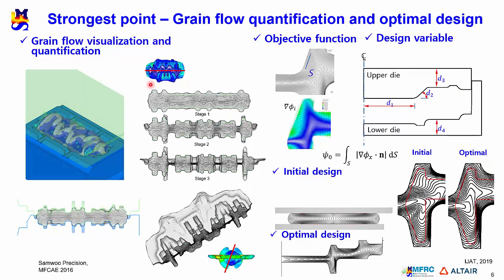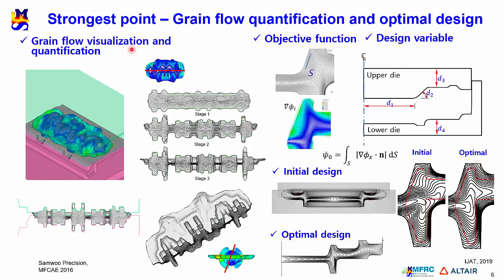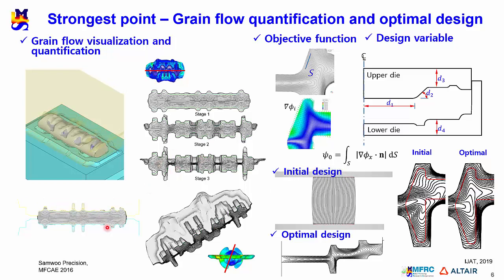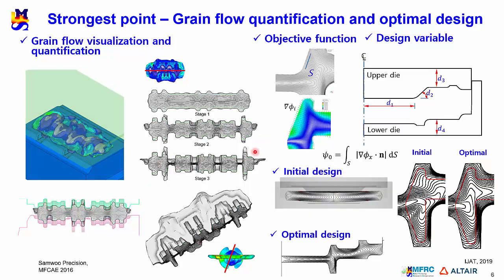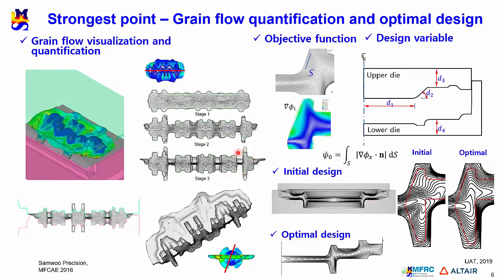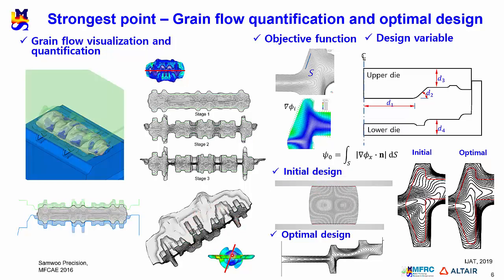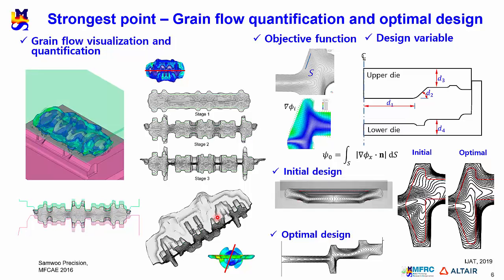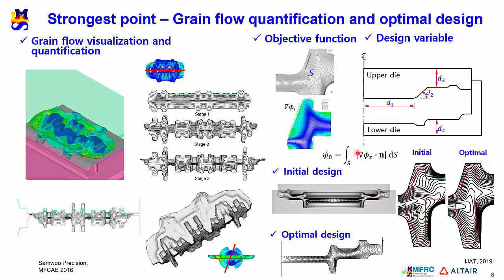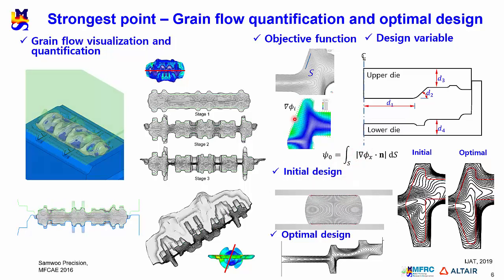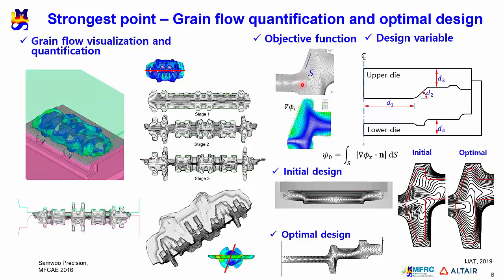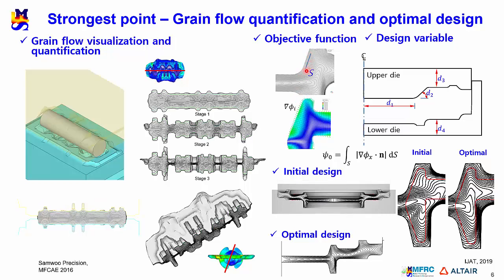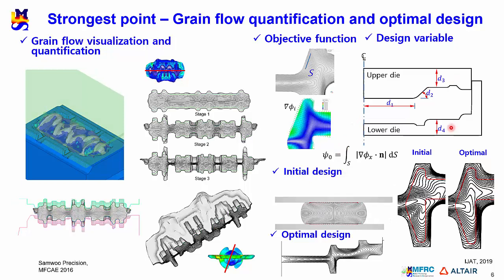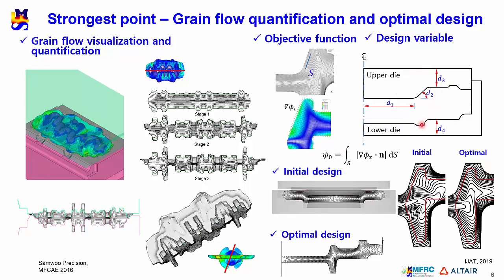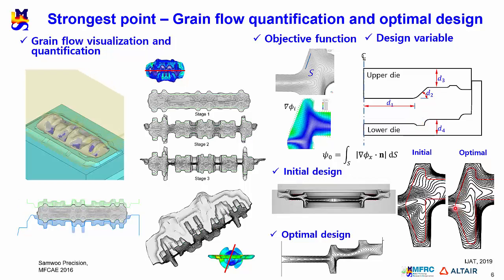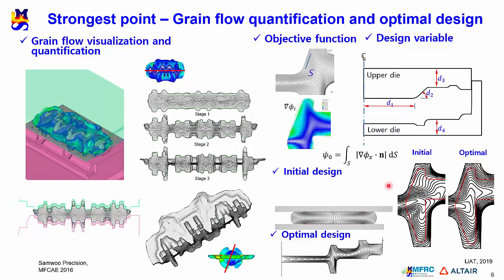From now on, I'm going to introduce some strong points of AFDEX. First, let me introduce how we can visualize the grain flow lines and use them for process optimal design. We developed a unique method to treat the grain flow lines not as a figure, but as a function, so we can visualize them at arbitrarily chosen sections immediately. So we can use this function as the objective function because normality of grain flow density, that is the gradient of the grain flow function to the surface that is generated by after-material removal, is important. We assign these geometric parameters as design variables, and we obtain these optimized grain flows starting from these initial grain flows.